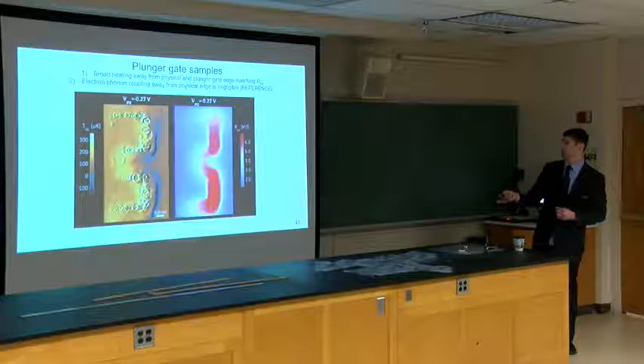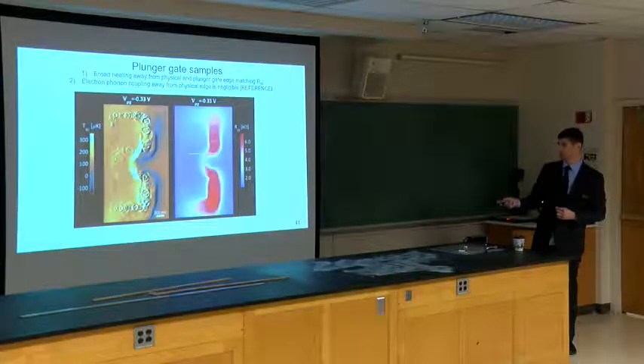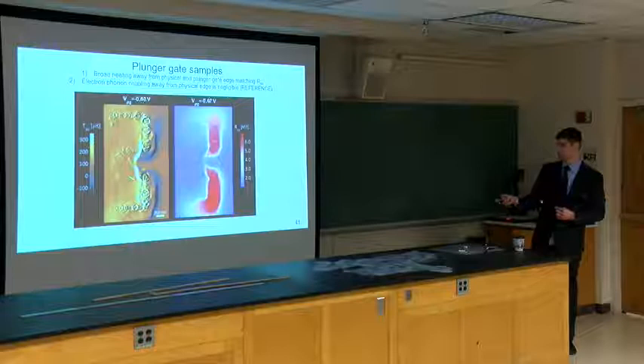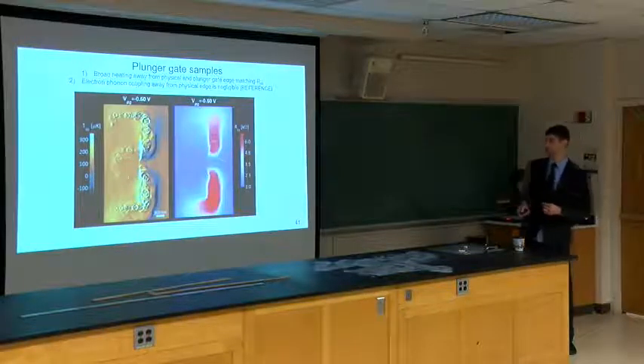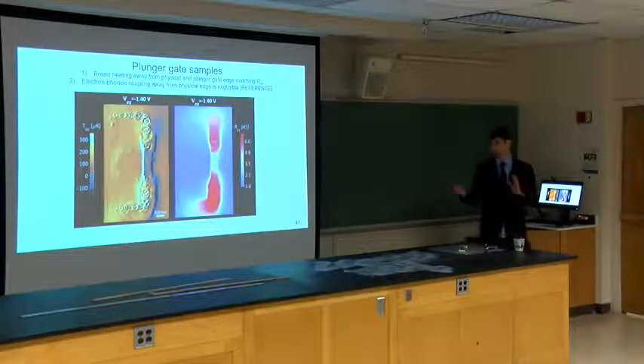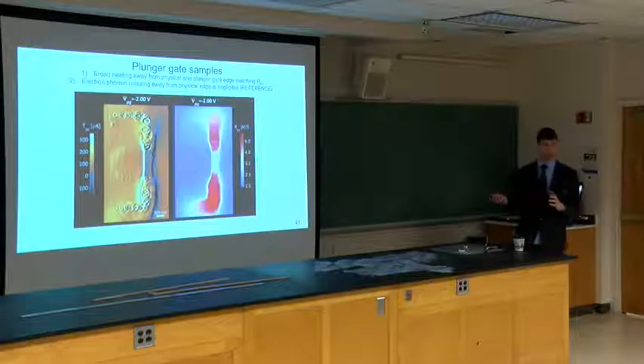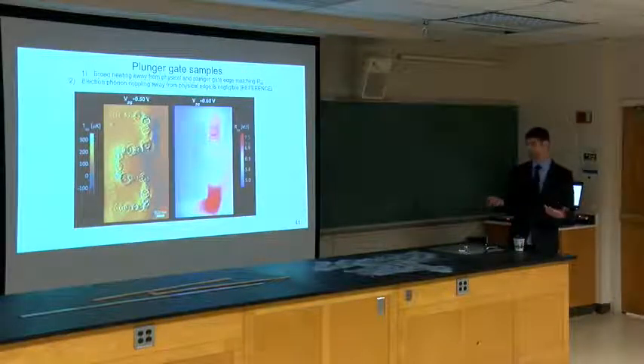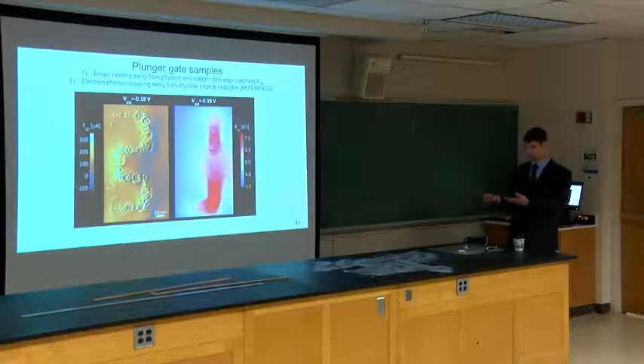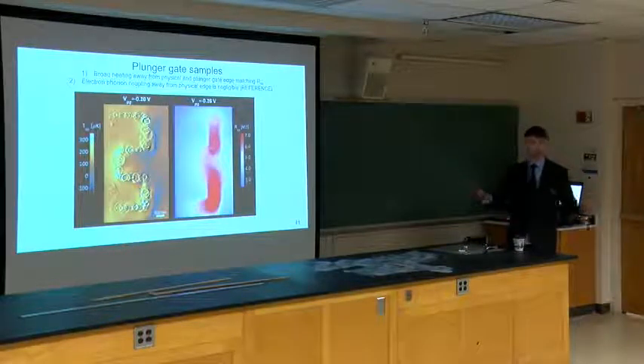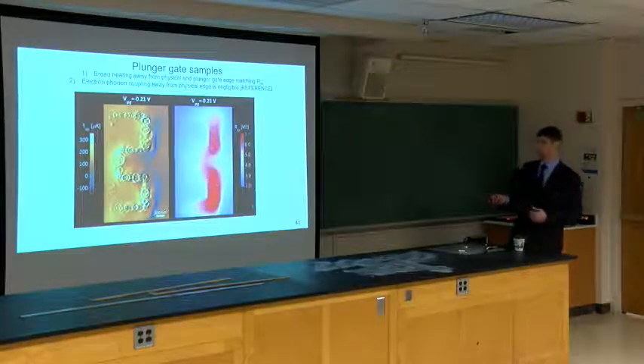And the edges are still lighting up, even when we move the current flow away from the edge. So I want to point out, electron-phonon coupling is extremely weak away from the edge. That's been observed in 2DEGs, and we see it if we're not in the quantum Hall regime. There's no scattering in the bulk.